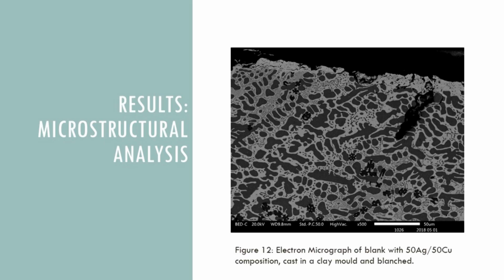So finally, I sectioned all of my blanks and gained microstructural data for each of them. Now, I found that the grain size observed when all of the blanks produced during the experimental investigation are actually much smaller than those found in the ancient examples, but all of the experimental blanks were left to cool slowly within their individual moulds. But despite this, the grain size is still much smaller. So this evidence could indicate that the ancient blanks were left to cool over much longer periods, or another potential explanation is that ancient moneyers were casting into moulds that were contained within a furnace structure and then allowed the entire furnace structure to cool after casting.